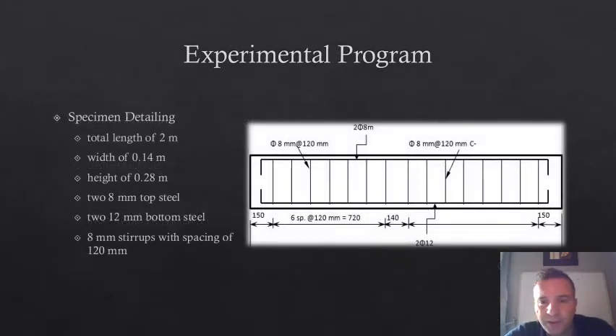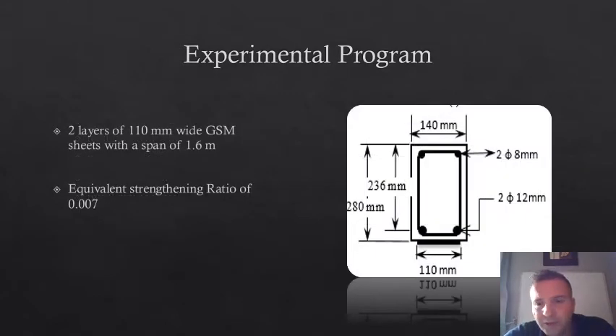So this is the control specimen. It's 2 meters long by 14 centimeters wide, and the height is 28 centimeters. It is reinforced by 2 number 8 bars on the top and 2 number 12 bars in flexure here, and you have 8mm stirrups spaced every 12 centimeters. This is a cross-section view of the beam, and this is the strengthening here. We use 2 layers of GSM sheet bonded with mortar, and they span over only 1.6 meters of the beam.